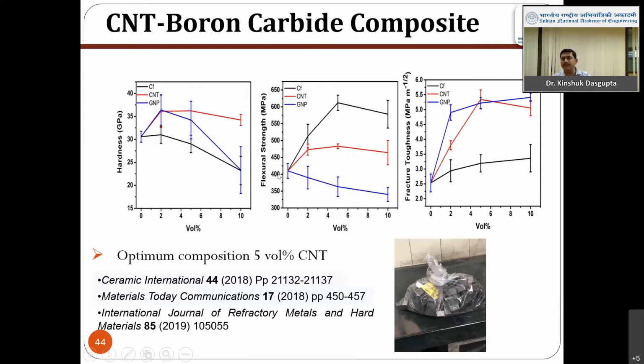Fracture toughness is very important because ceramics are very brittle in nature. So if we can improve the fracture toughness of the ceramic, their practical usability improves. If we see the fracture toughness, this is the third one. Once again with carbon nanotube, we get very good improvement, almost double the value. We also get that with graphene nanoparticle, but with carbon fiber not much. Then for flexural strength, we get maximum improvement with carbon fiber, but quite good improvement with carbon nanotube.